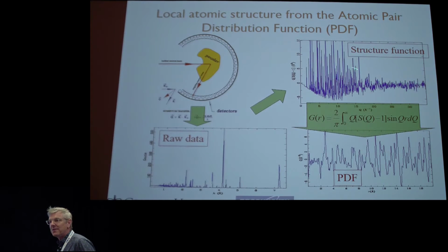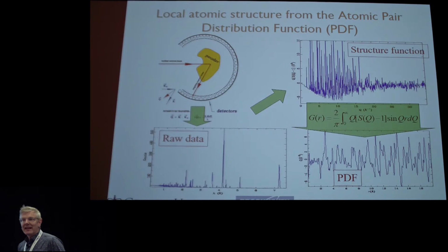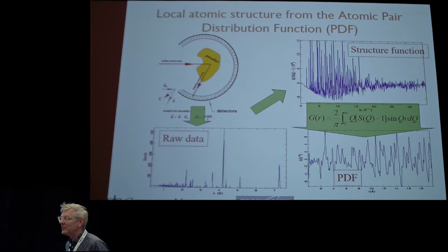And it looks like a forest of Bragg peaks here, and not like something you've seen before, maybe, unless you've done PDF work. And simply the reason is that we've measured over a very wide range of momentum transfer Q. And so this is like the d-spacing, this is like the diffraction angle. And if you do a conventional measurement with a copper K alpha source, you only get these peaks down here. But what we do is we use short wavelength X-rays or neutrons so that we collect data over a wide range. And then, as we were taught 80 years ago, by putting this through a Fourier transform relationship, we get the PDF.